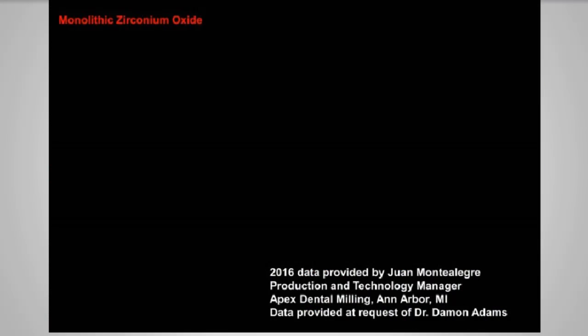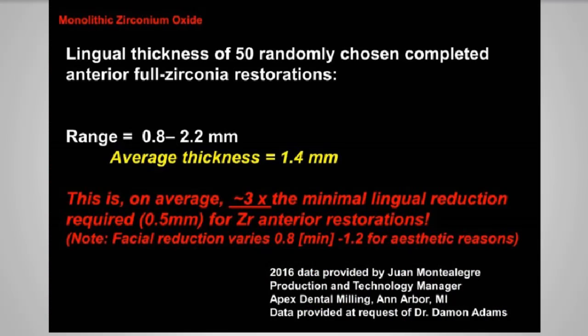At the same time, don't forget, we don't want to make these too thin either because we invite fracture even in zirconia, even regular zirconia. If you go below 5/10, that's not a good thing, and I'll show you the principle there with lithium disilicate in just a minute. Lingual thickness of 50 randomly chosen completed anterior full zirconia restorations: the range was 8/10 to 2.2 millimeters, and we found an average thickness of 1.4. This is on average 3 times the minimal lingual reduction required for zirconia anterior restorations.